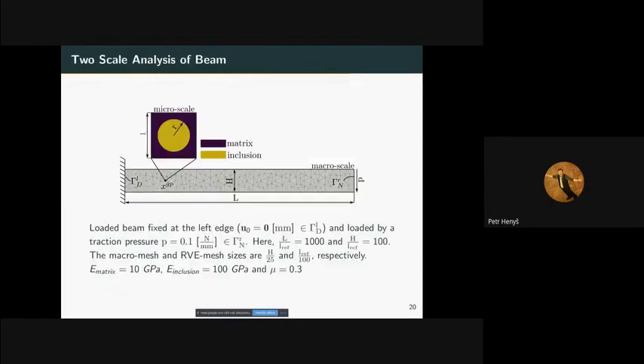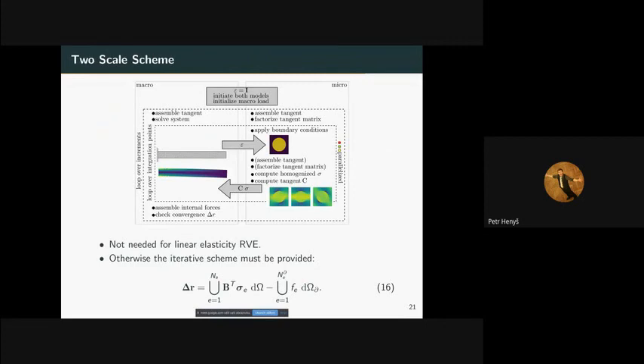Well, if you want to couple two scales, for example, a very simple example of a beam, which is composed from a very simple unit, which can also be considered a metamaterial with hard inclusions, then you can build up a scheme which is nothing more than a communication between the macro finite element model and the micro finite element model, right? Once you apply the deformation in the macro model, you will put it inside the micro model, and from the micro model you will get the elastic constants as well as the stress field, and this will go to the macro model.